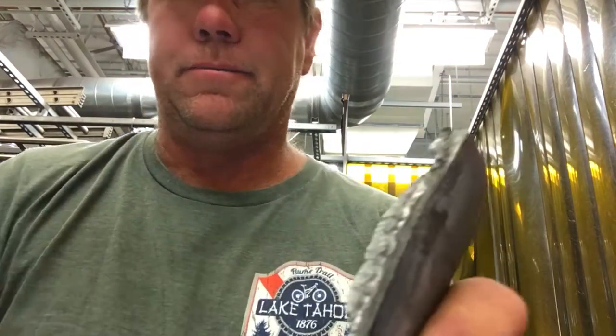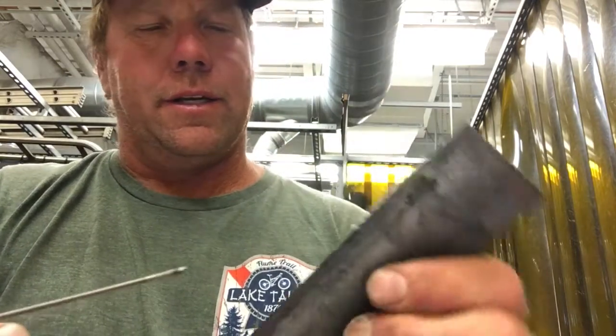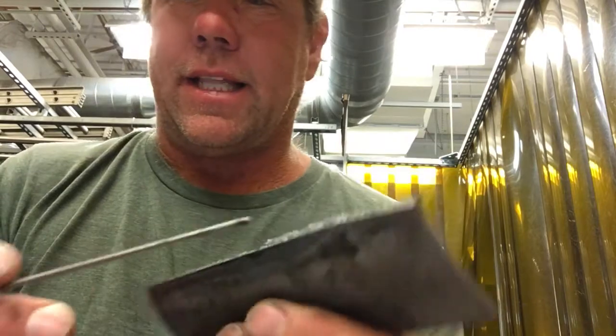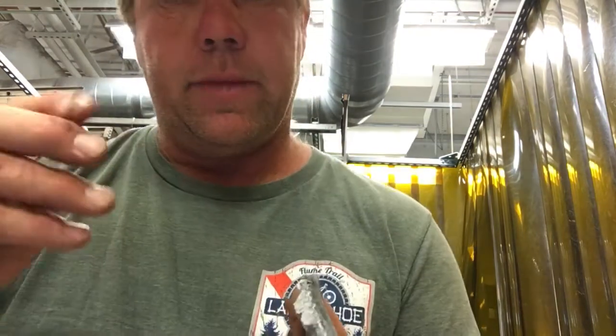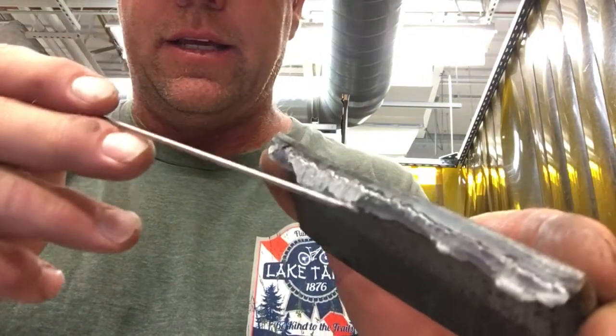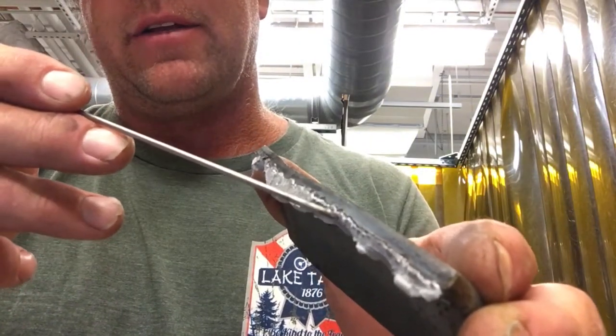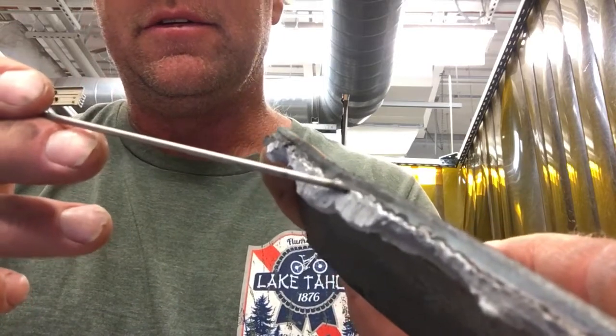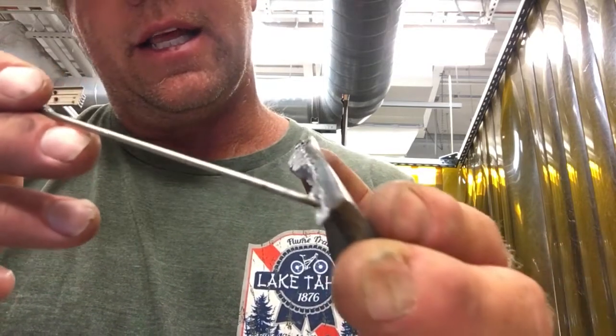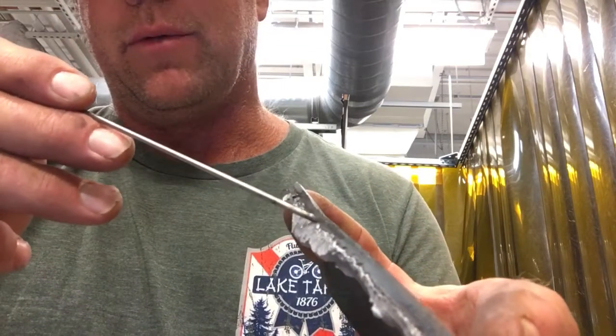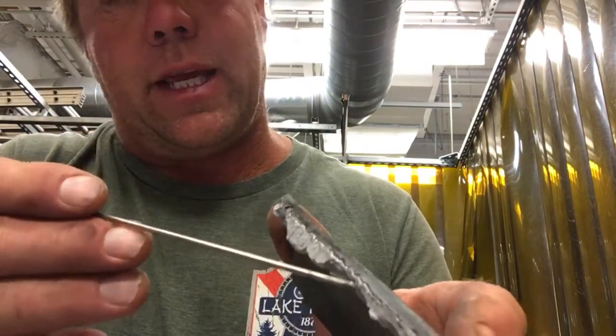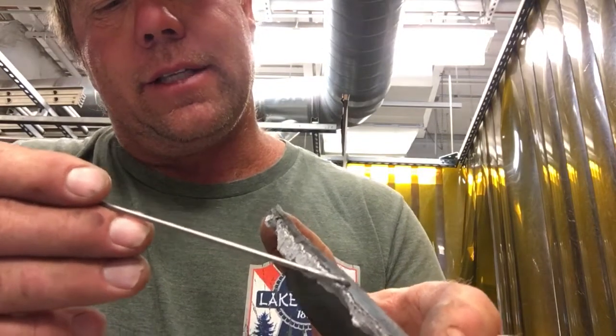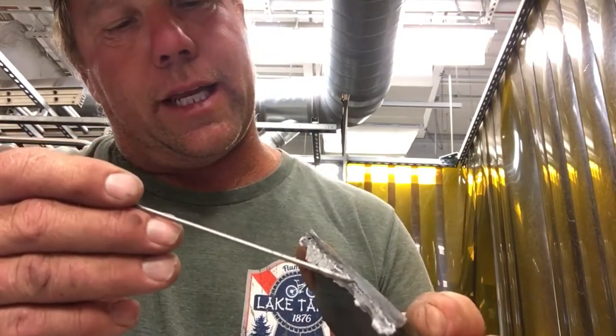Looking at the bottom here, any number of things going on. This is actually a slag inclusion, and it's not there anymore, so it's a little hard to see, but that little root right there, that little shiny zone, that's where slag used to be, but it fell out. And that was right at the root of the weld. That's why commonly you would do a weld, grind out the root of the weld, and then go back at it again to get all that out of there. This is what happens when you don't properly preheat. If I were to preheat this, now this would go away. So this is a function of the slag going to where it's cooling. It ends up collecting right in there just like that.